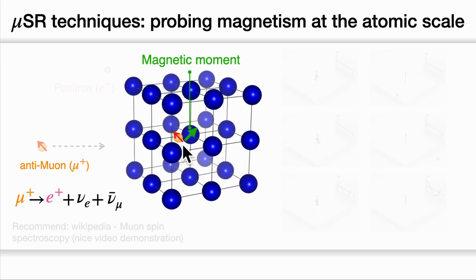In this muon spin rotation technique, people use anti-muons, which can decay into a positron and neutrinos. When we put muons into a material with magnetic moments, for example, this muon carries spin and this atom has a magnetic moment, equivalently a local magnetic field. This muon is under precession. After a while, it decays into a positron along the spin direction. Then we use a detector to detect positrons. By watching how they move over time, we can learn about the magnetic properties of the material at very small scale. For example, this muon decays into a positron, and we detect it.